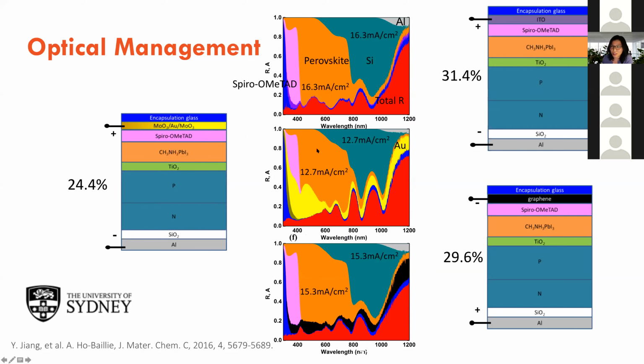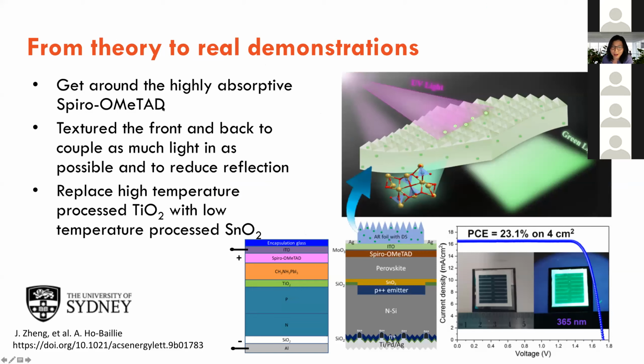Or one of my students is very clever. He said, well, why don't we get around it? So what he did was he put a down converter. So he infused some phosphor into a PDMS layer and put it on top of the solar cell. And this layer converts UV light into green light. So the spiro's got nothing to absorb. It's got no UV light to absorb, and it lets green light pass straight through. So that way the perovskite is able to enjoy the high energy wavelengths. And he's managed to find some really very efficient down converter.